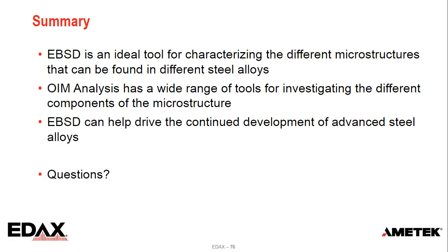And it also will depend on the acceleration voltage you're looking at. I mentioned the iron carbides: Stefan Zaefferer and his group at MPI in Germany showed they could go to lower voltages, say 20 to 10 or 12, and could resolve more of the carbides at finer phases. Also realize that at 70 degrees tilt, we have a projection of the interaction volume along one direction of the sample. So your spatial resolution is not necessarily uniform, both along the direction and against the direction of tilt, and sometimes you have to take that into account as well.